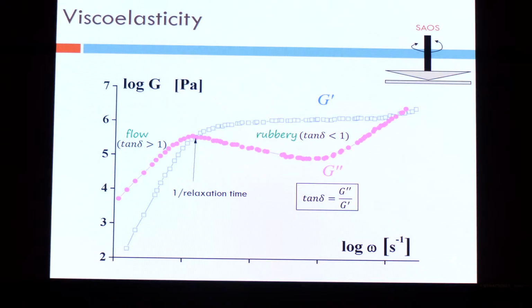Now the elastic part, the blue part, is higher than the viscous part, which is the pink part. Which means now the material behaves more like a solid, because you're doing high frequency motions, that is, the time is very short, that time is not enough for the polymer to relax, and therefore you get an elastic response. So you get a behavior that looks like almost a rubber. So on the left you get a flow response like a liquid, on the right you get an elastic response like a rubber.